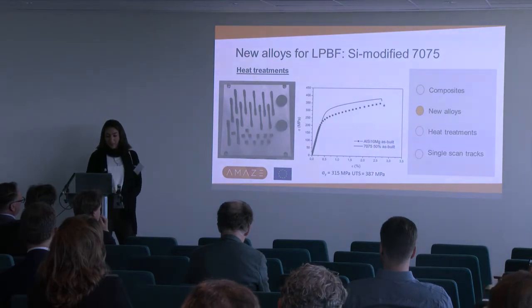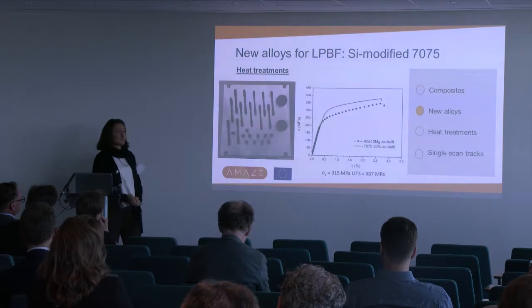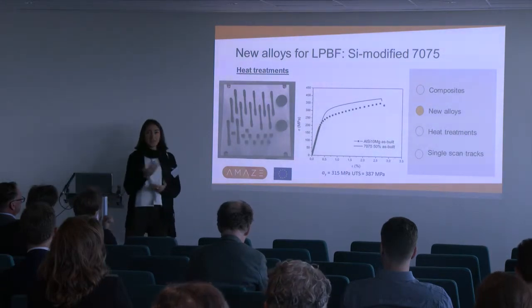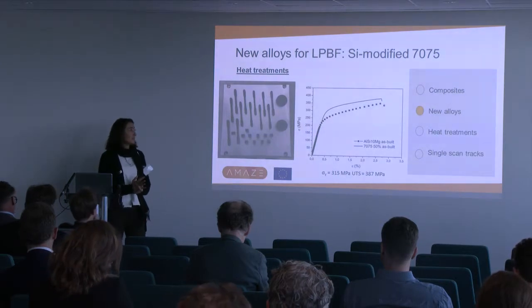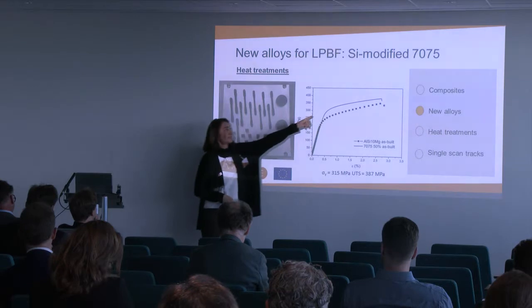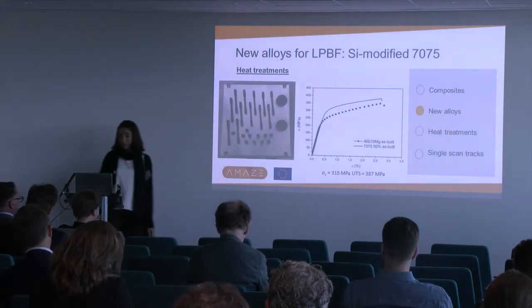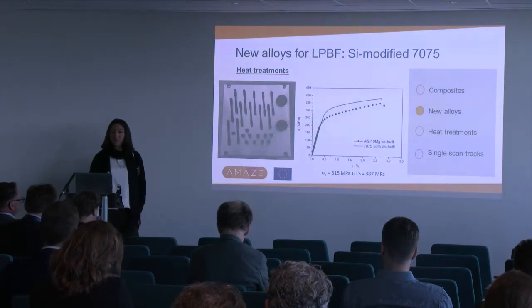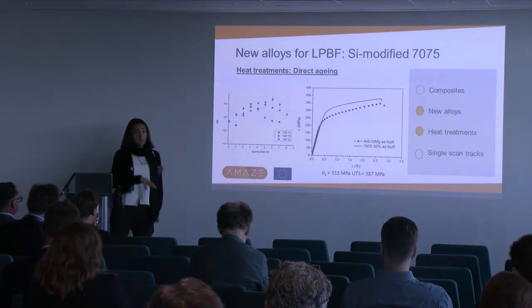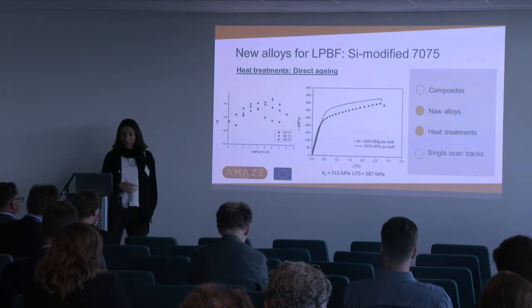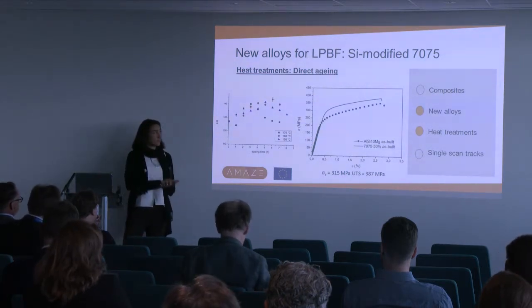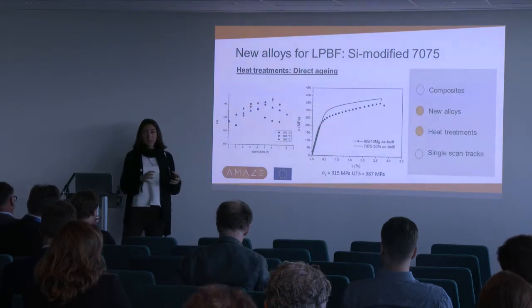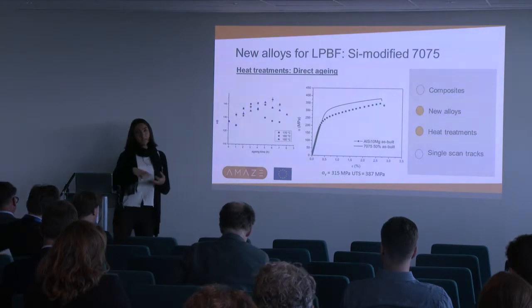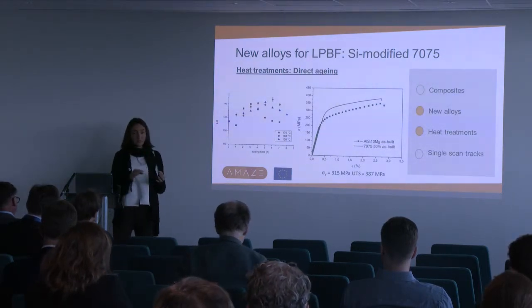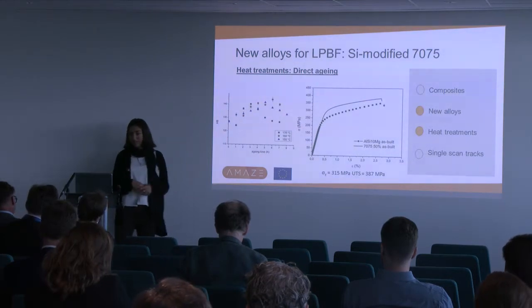So we built these samples with some parameters, and if we check the mechanical properties, it was interesting to find that we could achieve higher mechanical properties than the aluminum silicon 10 magnesium alloy. So here we have the curve of the modified 7075, and that one. So we could reach 315 as yield strength, and 387 as UTS. Then we thought, why not perform a heat treatment on this alloy? So we can consider that because of the fast cooling that arises during the laser scanning, the samples are in a supersaturated solid solution. So we can do a direct aging, so age the part and allow the alloy elements to precipitate in the sample.